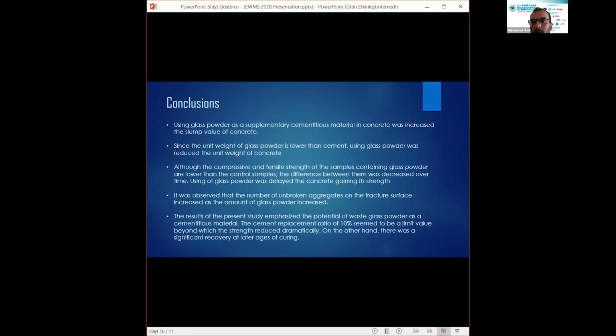Conclusions: using glass powder as a supplementary cementitious material in concrete increased the slump of concrete. Since the unit weight of glass powder is lower than cement, using glass powder reduced the unit weight of concrete. Although the compressive and tensile strength of the samples containing glass powder are lower than the control samples, the difference between them decreased over time. Using glass powder delayed the concrete gaining its strength.